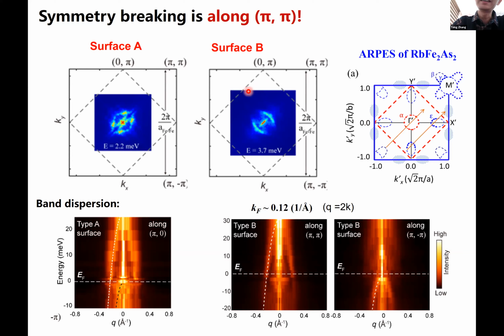But here I want to say that this map is FFT, so it is in the Q space. If we assume it's not a direct mapping of the Fermi surface, it measures the scattering between the Fermi surfaces. So usually for a round-shaped Fermi surface, Q equals 2K. So this pocket, if we change into K, it should be only half the size of this pocket. So it appears to be a little bit smaller than the ARPES-measured Fermi pocket. So actually, we're not sure if the band measured by QPI is the ARPES-measured one. But the band dispersion is clear. It is a hole-like band.